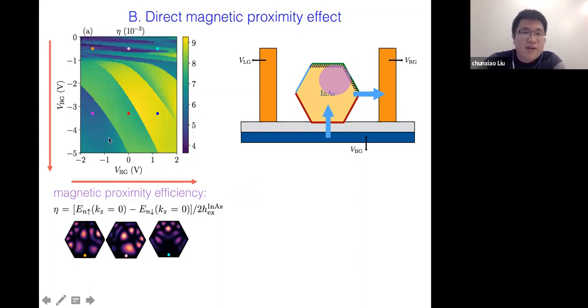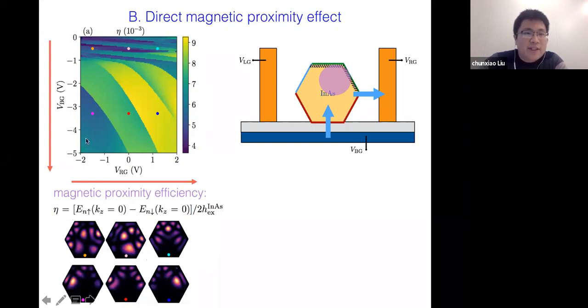We plot several wave functions for this indium arsenide here. These three wave functions are the subband modes when the backgate is close to 0 volts. You can see that the wave function is spreading almost all over the indium arsenide cross section. And then when the backgate voltage is more negative, like these three dots, the wave function will be confined, pushed upwards. So this is consistent with our toy model analysis.